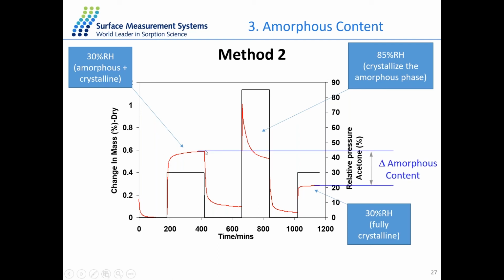And as you can see, there is a difference between the first and the last stage 30% RH step. And this difference in the mass is because of the amorphous content of the material. And we have a standard material for the calculation as a reference, and by percentage to that standard material, we can then calculate what the amorphous content of the sample of interest is.